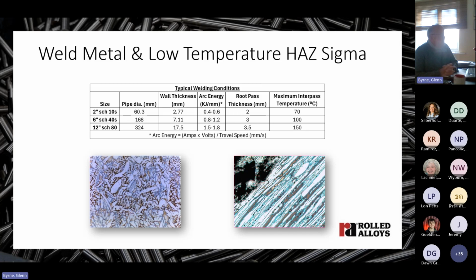In multi-pass welding, you're continuously reheat treating, so the balance is to make the beads as big as possible without causing them to be sigmatized, and minimize the total number of weld passes and thermal cycles that take you up into the sigma sensitive temperature range. So if you can do that, you have a really good chance of avoiding sigma. Now, the required welding parameters and techniques to avoid this are really very well known. And this table gives some examples of arc energies, root pass thickness, and maximum interpass temperatures for different sizes of pipe. And this sort of information is available from very many welding consumable suppliers.